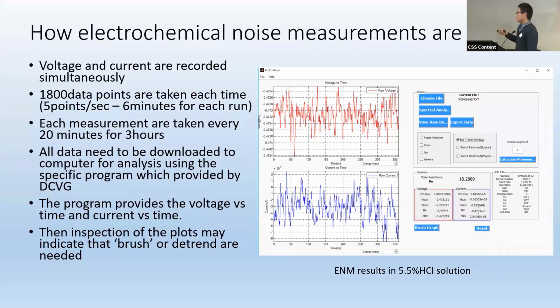All the data has to be downloaded to the computer and analyzed using this software. As you can see, you can get those plots, voltage versus time and current versus time. After that, this software can calculate the resistance value. First of all, when you get those results, the first thing is to inspect those plots to see whether they are good or not, and this may indicate the further analysis and the detrend function.